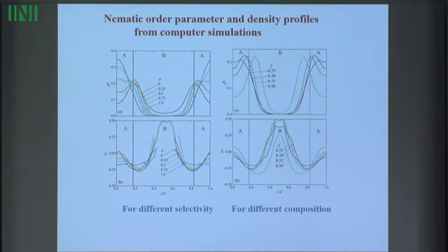And again, there are also curves for the nanoparticle concentration, so there is indeed a net orientational order in this system. This is quite interesting from my point of view, because that is a completely different system from ordinary liquid crystals. Here, anisotropic objects are orientationally ordered not because they interact with each other, but because they are coupled to the structure. So that is essentially a broad surface effect.